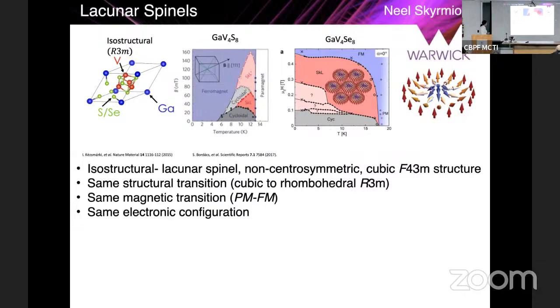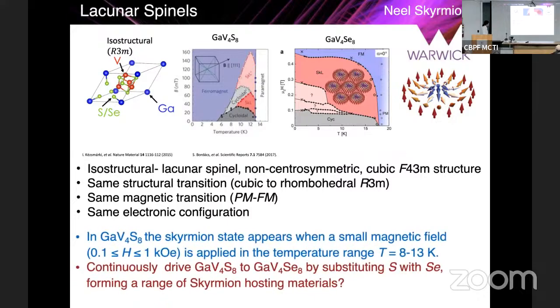Now, both gallium vanadium four sulfide (GaV4S8) and gallium vanadium four selenide (GaV4Se8) are isostructural. They adopt the same structure at room temperature. It's a non-centrosymmetric cubic F4-3M structure. They both undergo the same structural transition from cubic to rhombohedral at low temperatures. They also undergo the same magnetic transition to the ferromagnetic state. And from a chemistry point of view, they are very similar in the electronic configuration as well.